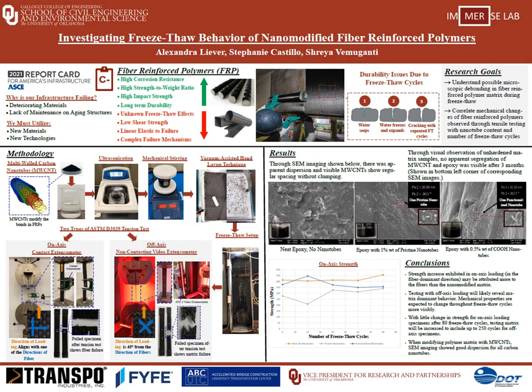Because there is not an obvious trend visible, we concluded that the number of freeze-thaw cycles should be increased to see long-term damage. This also spurred our decision to do off-axis testing to isolate the matrix behavior, since the freeze-thaw may be affecting the matrix more significantly than the fibers, which account for most of on-axis strength. Trends in strength are expected to be more visible with this method.